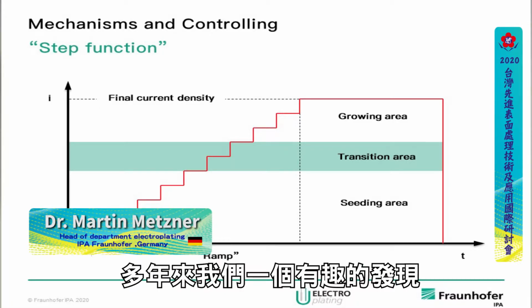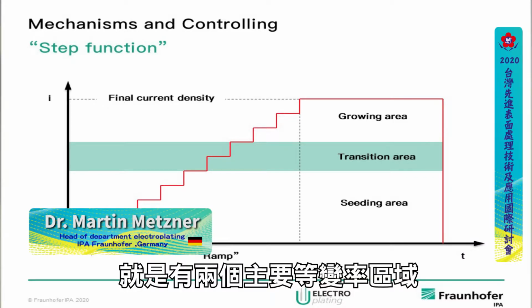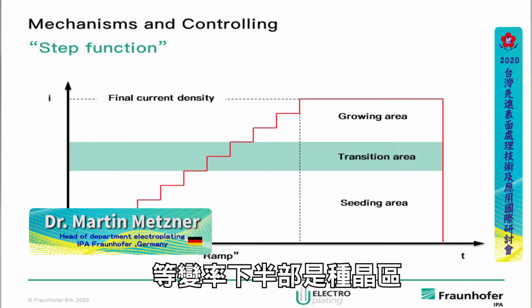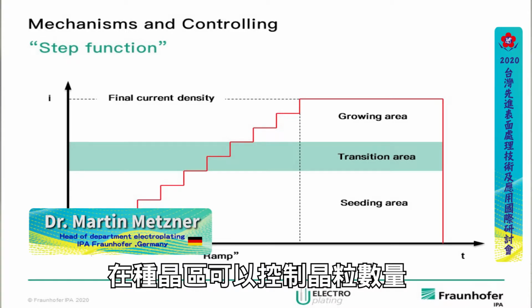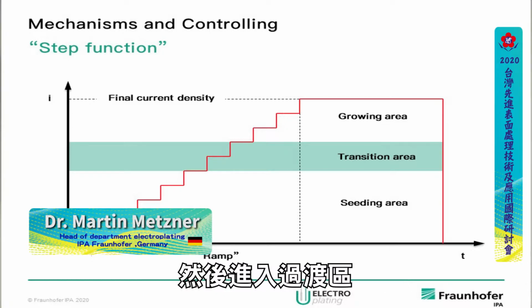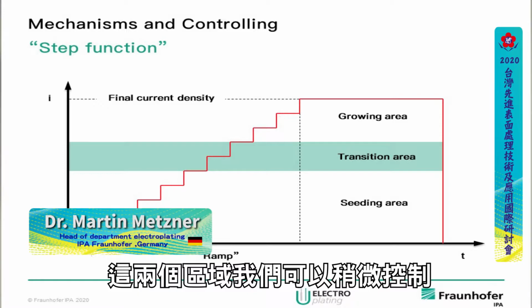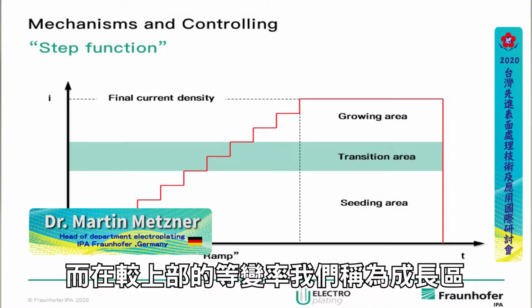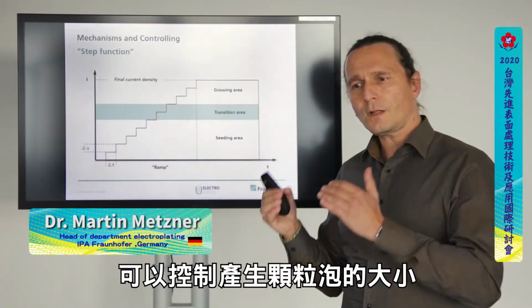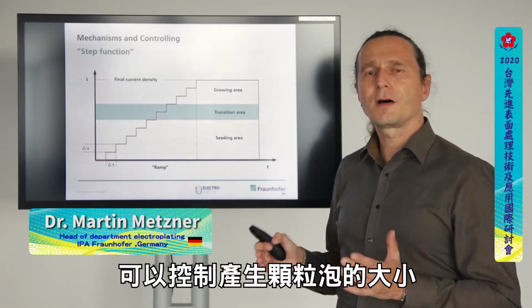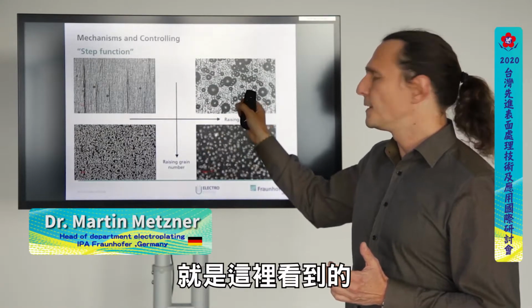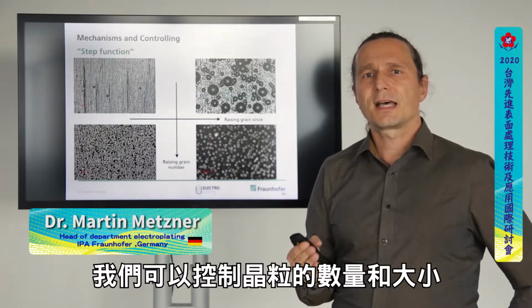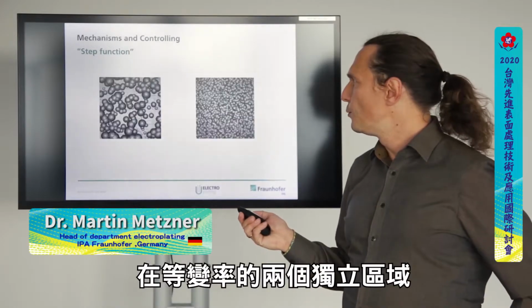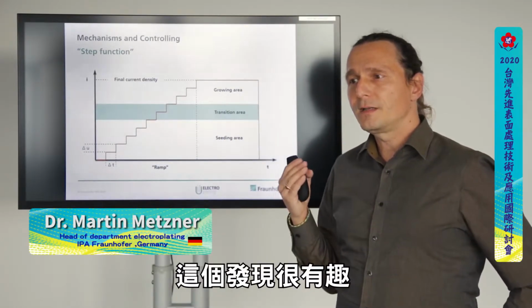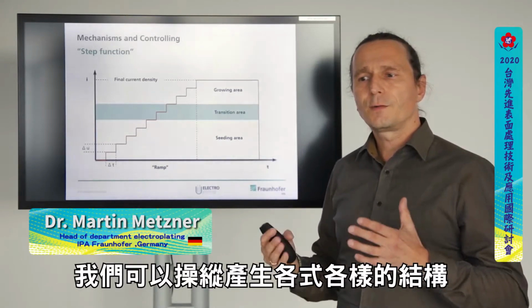And what we learned, and this is the interesting thing over the years, is that we've got two main areas of our ramp. The lower area of our ramp is what we call the seeding area. In the seeding area, we can control the number of the grains we build up. Then we've got a transition area, where we can control both of them a little bit. But generally speaking, the higher area of our ramp is what we call the growing area. There we can just control the size of the grains we build. So we can control the number and the size of the grains, the structure elements we build, with two separate areas of our ramp, which makes it very interesting because we can play around in a very broad range of different structures.